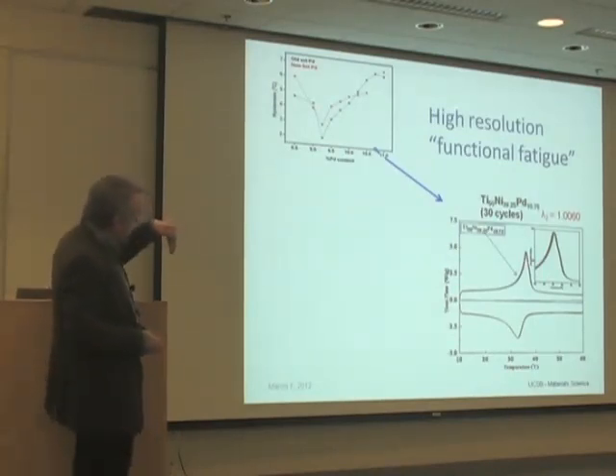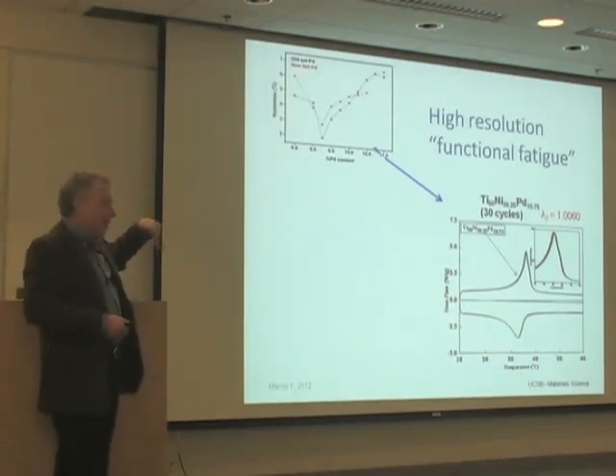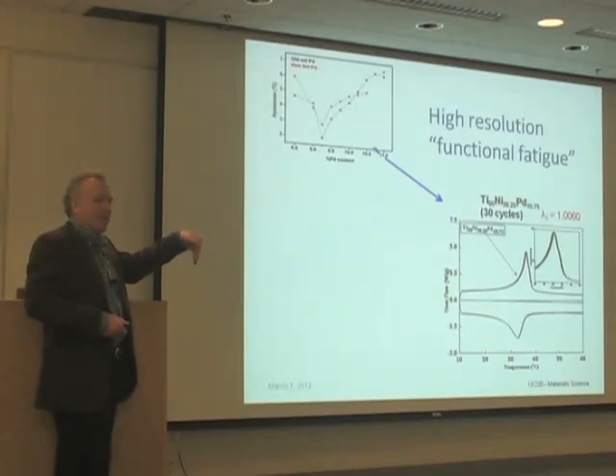That's migration of the phase transformation temperature with cycle. And that's a known effect. It won't keep migrating forever. It migrates and then it eventually saturates. But that's considered a signature of damage in the material.